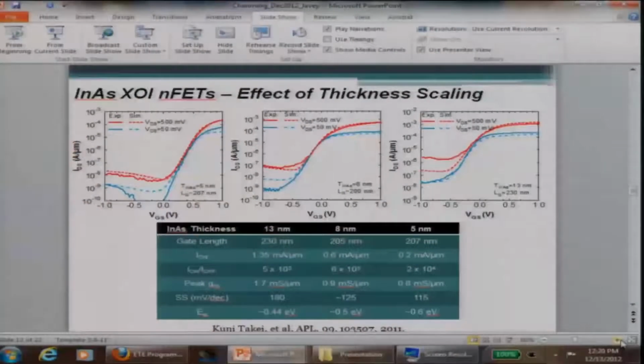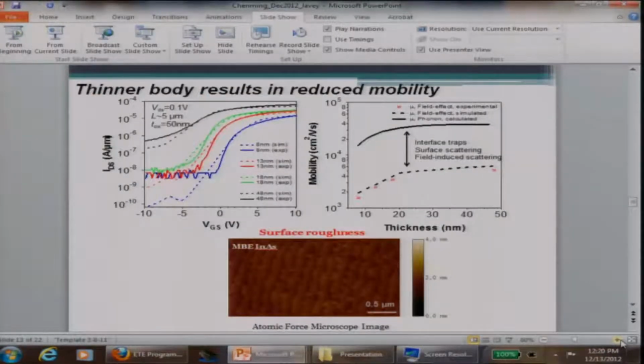Now this subthreshold swing is still not perfect, and I will show you a little bit later that now we have improved this, and we can now get 70 or 72 millivolt per decade for our devices by doing proper treatment. So based on this, thinner indium arsenide is better. So you might ask yourself, are there any disadvantages to using thinner indium arsenide? And the answer is yes, mobility.